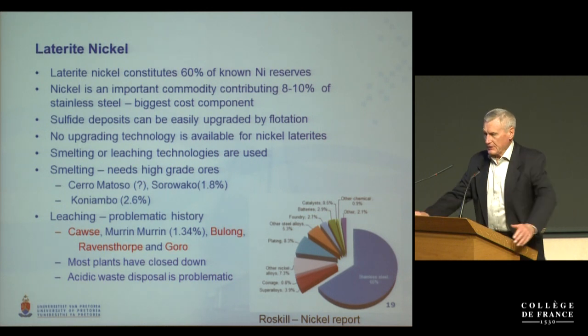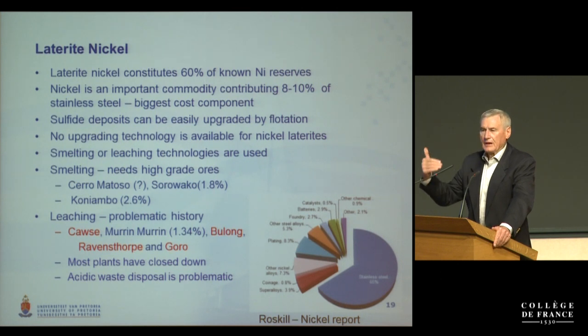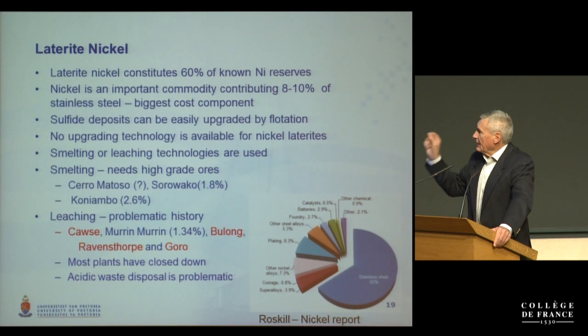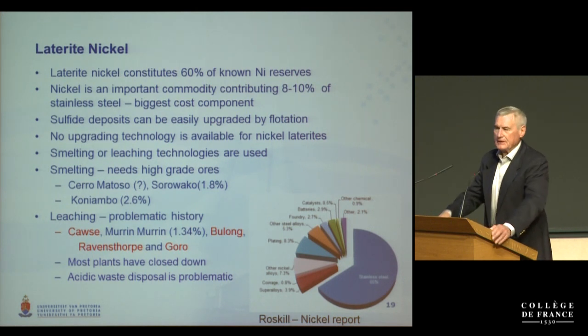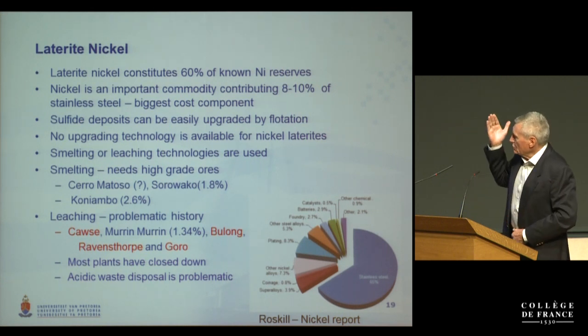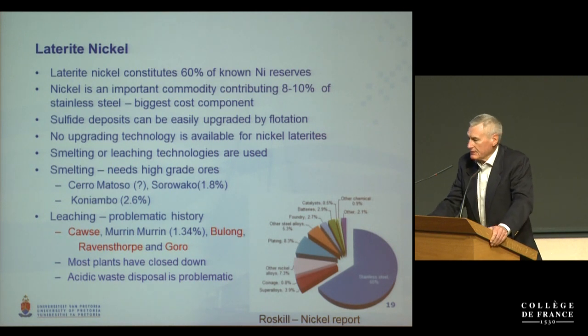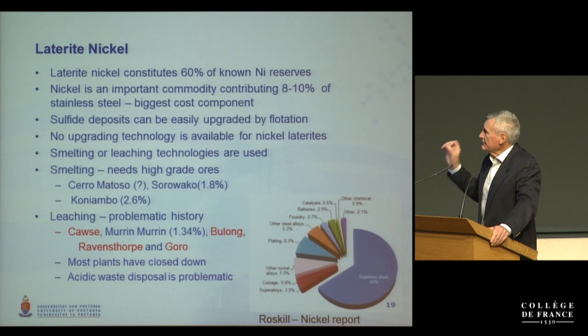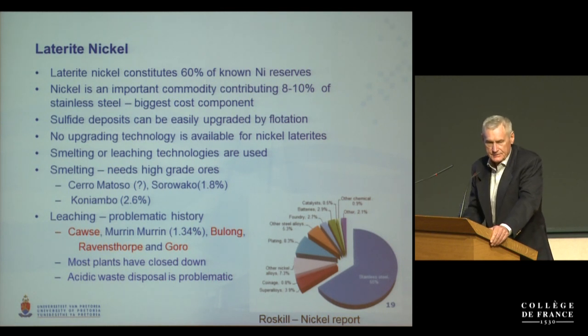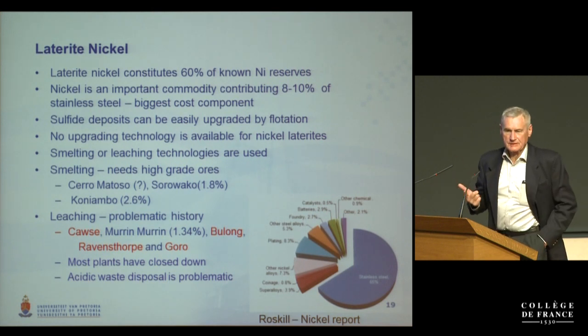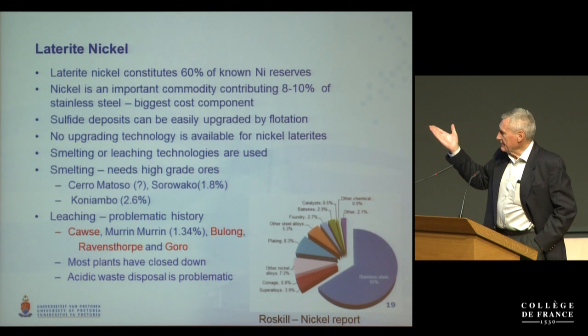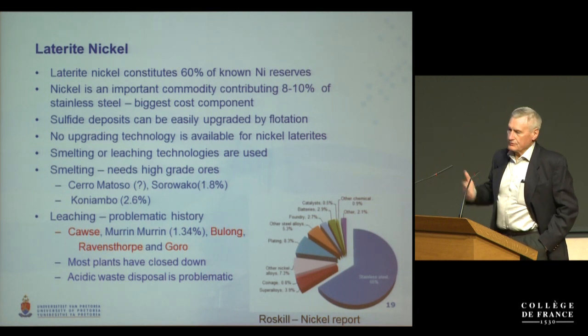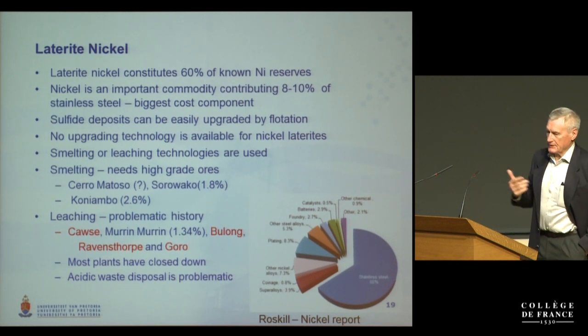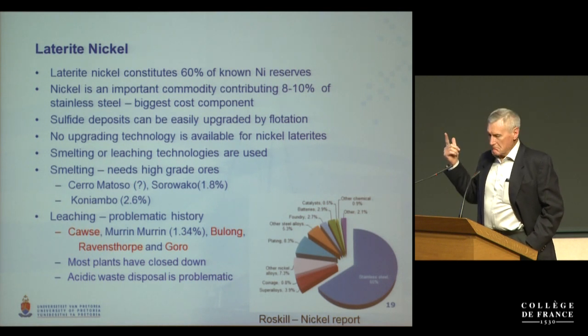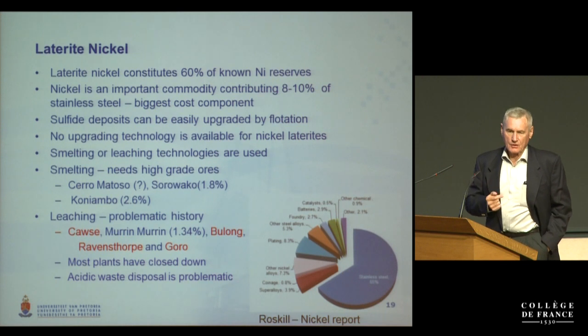And sulfide deposits are essentially known and exploited, and they can be easily upgraded by flotation, and therefore you could easily treat the upgraded concentrate by various metallurgical methods. However, for laterite nickel, there is no known way of concentrating the nickel in the laterites. So therefore, you need to smelt this material as is. You can see the grades, 1.8% at Sorowako, Koniambo, 2.6%. And in Australia, leaching was another opportunity, but most of these mines, indicated in red, are no longer operating.